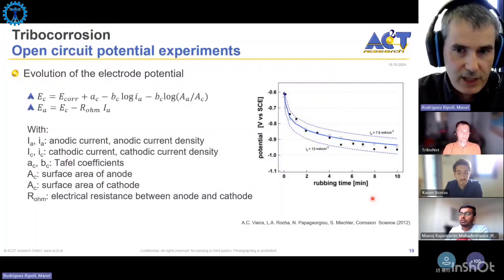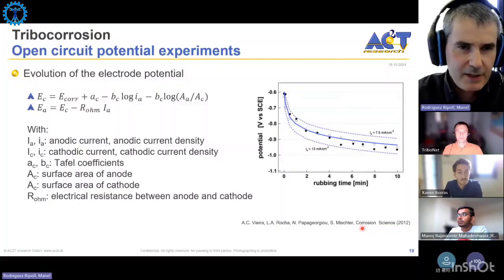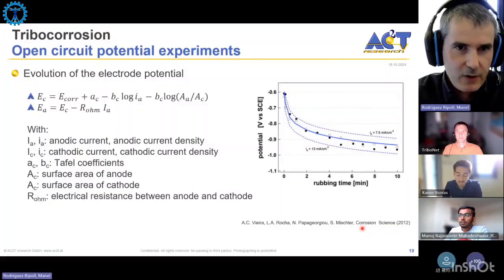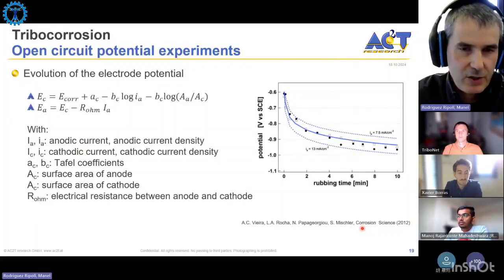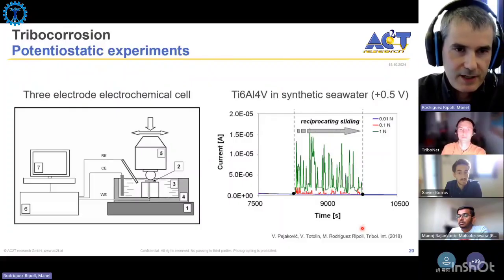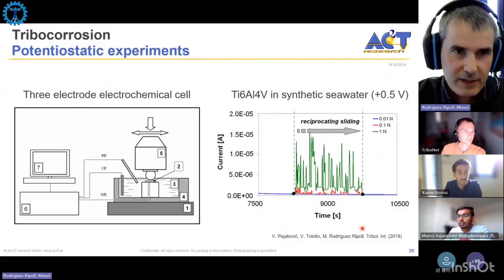You have all the equations here in the paper with all the explanation, but you can also get quantitative data out of these open circuit potential experiments. It's usually not done, so typically OCP experiments are discussed qualitatively, but it's possible to get quantitative data. The place where quantitative data is typically obtained is using potentiostatic experiments.